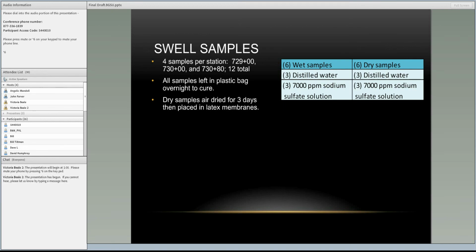This is what the samples look like. We had 2 chests, so one had distilled water in it, and one of them had the sodium sulfate solution in it. So there were 6 samples in each chest. And there was a porous stone on top of the sample as well as on the bottom of the sample. So the sample was never in direct contact with the water or sodium sulfate. That solution would wick up through the porous stone into the sample.